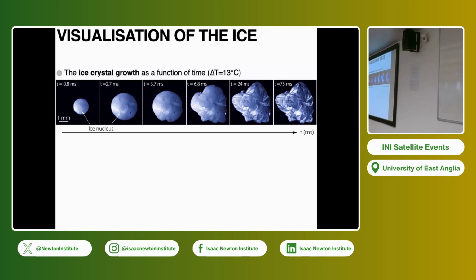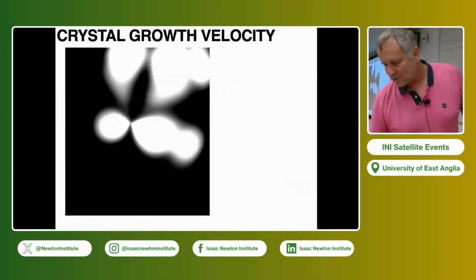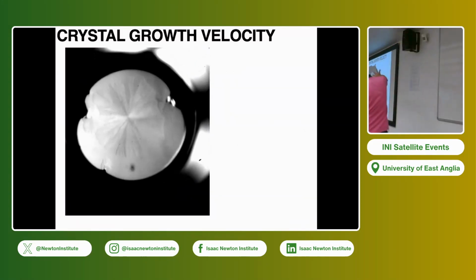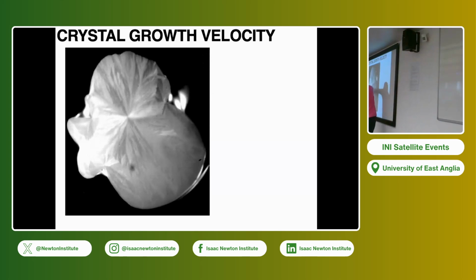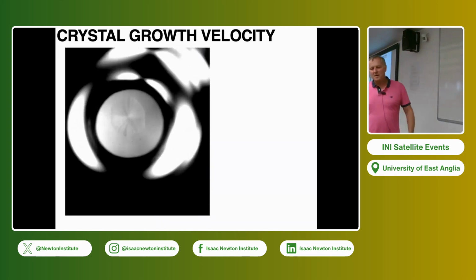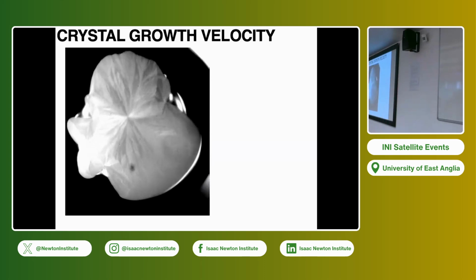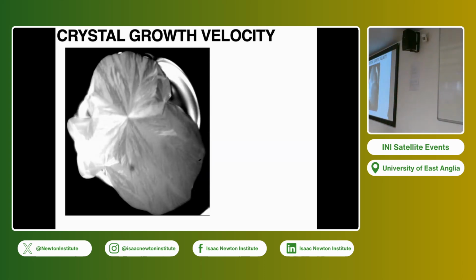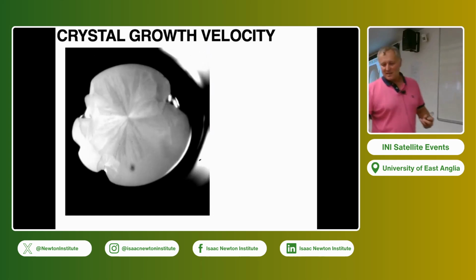As you can imagine, we have identified that these are ice crystals, ice nuclei that are created at the interface, and these ice crystals move, and as they reach the contact line, somehow they stop the contact line. So this is what we seem to observe. Actually, if you look at a movie, you can see that. It's less clear than the figure because we take it with color, but you can definitely see that there is like a race between the spreading of the drop and the crystal. And why is it a race?